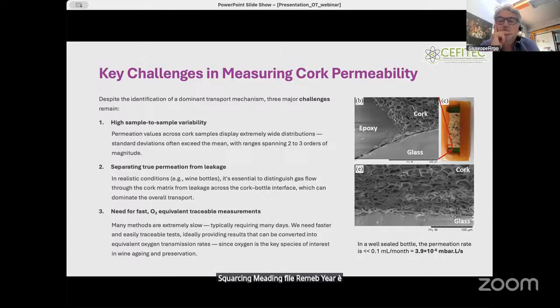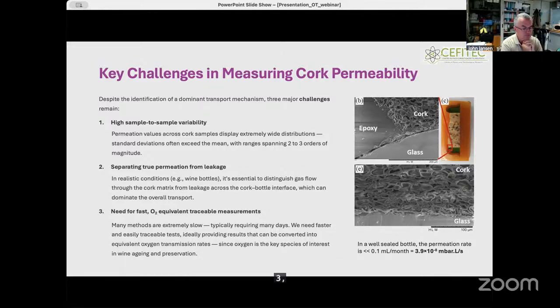So just to situate us in the measurements, we saw from Paolo numbers in 10 to minus 14 millibar liter per second per square centimeter, if I remember. Oh, yes. Here it is below 10 to minus 8 millibar liter per second. And this is the range, at least one order of magnitude below. Okay, that's it. Thank you.